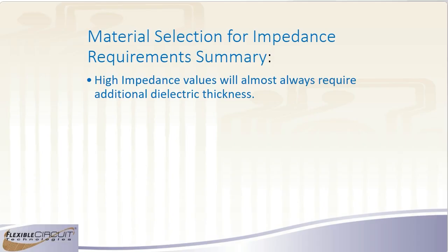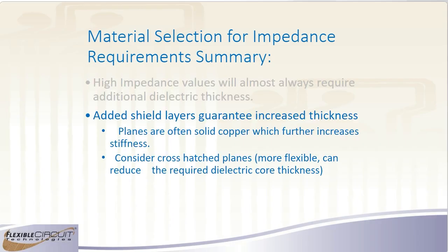So when you are doing high impedance, or typically elevated impedance, because the standard flex circuit, when you don't take anything into account, is going to be a much lower impedance value than most systems need. So once you start elevating, trying to get up to 50 ohm strip single-ended or 100 ohm strip line or 100 ohm differential, you're almost always going to have to add additional dielectric thicknesses to spread your signal traces from your planes. Those added shield layers are going to increase your thickness because you're adding additional layers. The planes are typically solid copper, and so that's going to add more stiffness.